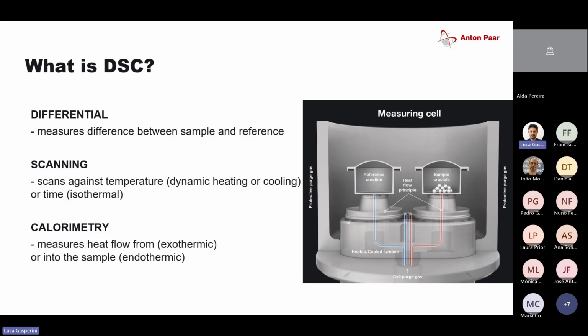Differential because what we do measure is actually the difference between the sample and a reference. Scanning because we scan against temperature or time. If it's against temperature, we either heat or cool the sample in a dynamic way, or we can keep the sample isothermally at a given temperature for a certain period of time. And calorimetry comes from the Latin calor, which is also in Spanish, not sure if in Portuguese, which means heat, perfect. So we measure the heat flow either from the sample or into the sample, and then we can distinguish between exothermic and endothermic processes.